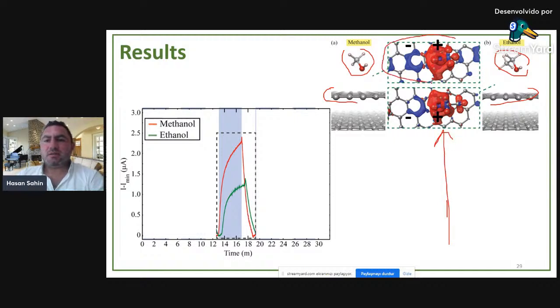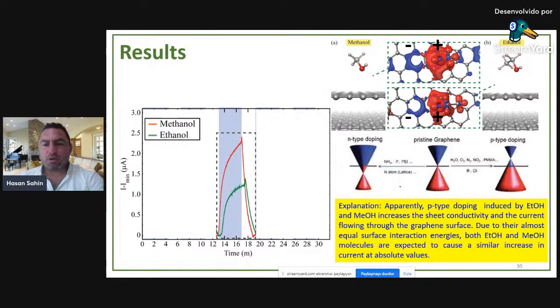here you see that there are minus and plus signs. The minus sign is for these blue charge densities, and the plus sign is used for the red colored. It seems that if methanol or ethanol approaches the surface, it disturbs the charge density distribution on the graphene. So kind of doping occurs. The whole explanation is apparently that p-type doping induced by ethanol and methanol increases the sheet conductivity.